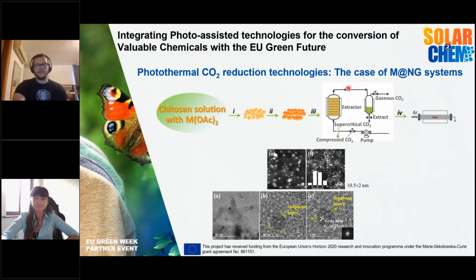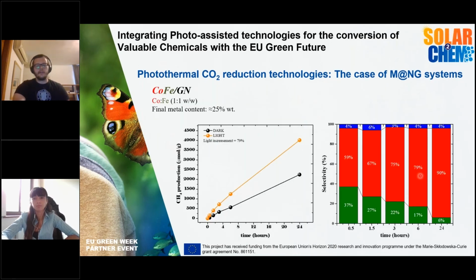Going to a more specific study that we disseminated this year, we obtained from chitosan and from different metallic precursors our scaffolds with a very easy procedure. We beaded the polysaccharides already impregnated with the metal. We dried them and then pyrolyzed them to obtain those very high quality catalysts with a very good dispersion and also good particle sizes.